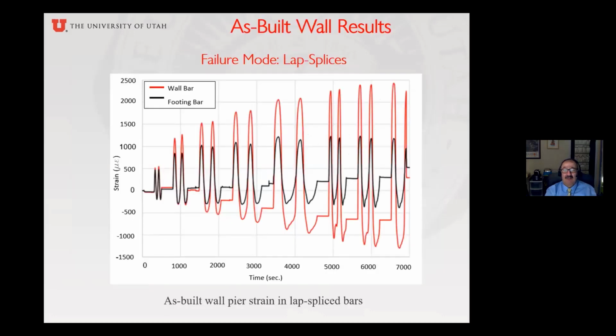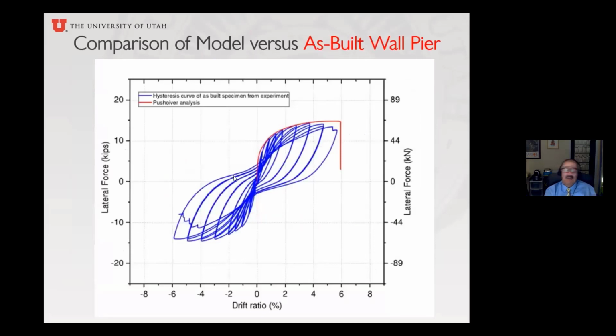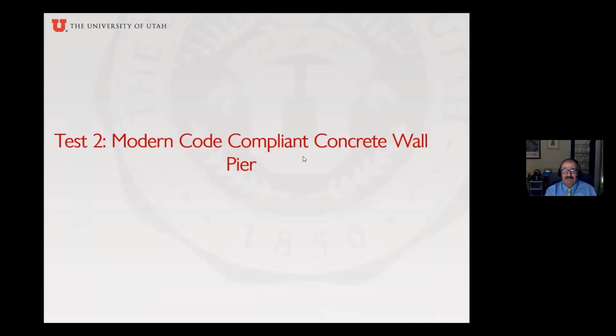And here you can see why we know the lap splices fail, even though there's not a good picture. We see that the footing bar and the wall bar actually are very far apart. That means that the tension is not transferring through the steel. And here you can see that our prediction actually wasn't too bad. It's the red line, and the blue line is the test.